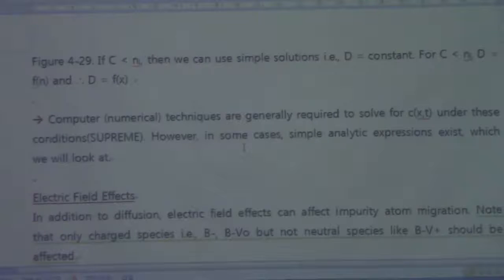In semiconductors, a concentration gradient does create an electric field. Let's suppose you have a concentration gradient along the depth, along the distance. Then this dopant concentration will create a potential difference, of which the slope represents the built-in electric field inside the semiconductor.